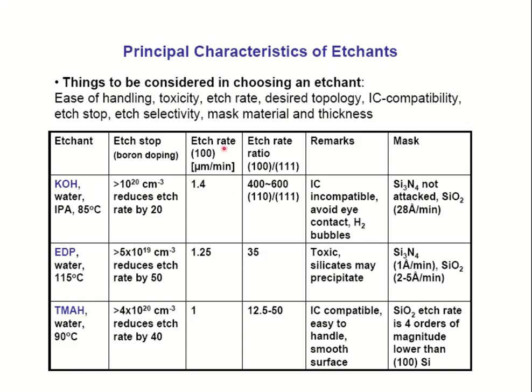For the KOH, the etch rate in the 100 direction is 1.4 micron per minute, and then this is 1 micron, and the ratio of 100 direction over 111 is, so how much is for the anisotropic etching, KOH is much higher than the other two. So to have a good 54-degree anisotropic etching rate, you should use KOH because their etching rate is much different from the other two.